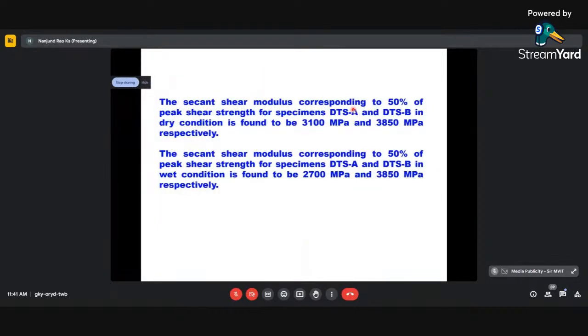So what did we get? The secant shear modulus corresponding to 50% of peak shear strength. That means you are computing shear modulus not at full, only at 50% of peak. That is two kinds of specimens. They have found 3100 to 3850 megapascals. That is the G, the secant shear modulus corresponding to 50% peak shear strength of specimens. These two in wet condition: 3100 became 2700, and 3850 continued to remain 3850 in the wet case also for this particular specimen.